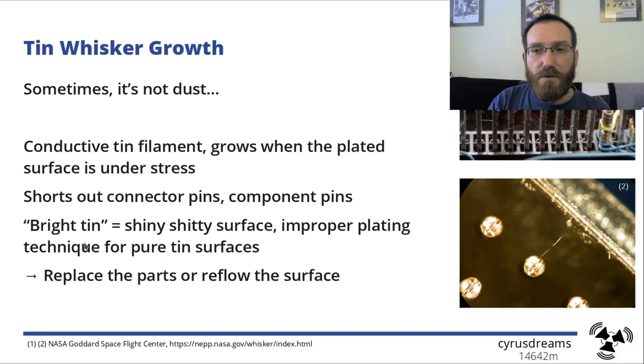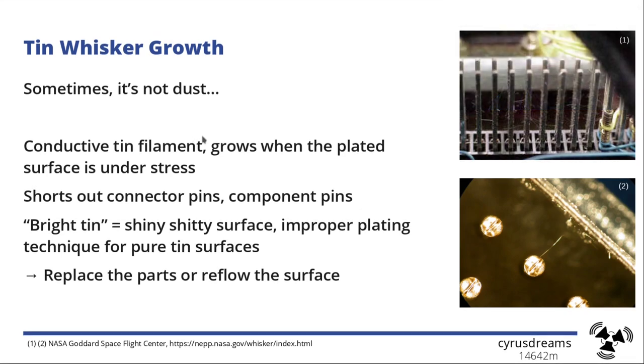And the most likely surfaces to have whisker growth is bright tin, which is the shiny connector shells that are really reflective. They're really bad because they are prone to grow whiskers like crazy. So don't use something like that. Get something that's matte tin plated. That one will last a lot longer without messing up your hardware.